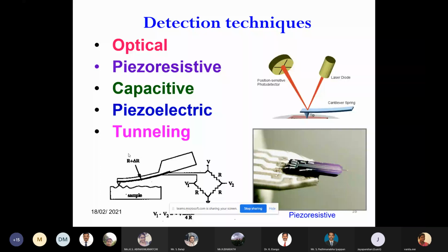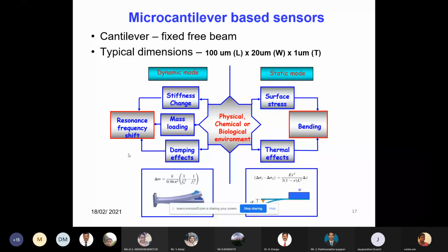This is the readout. With this readout, you can get even micro or nanostructure deflection, in the case of a static mode or in a dynamic mode. The resonance frequency shift can be monitored. Then these are the applications of the microcantilever. In our laboratory, we use a commercial microcantilever, 100 micrometer length, 20 micrometer width, 1 micrometer thickness.